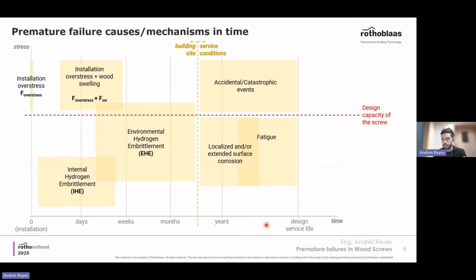We installed the fastener to the design service life. Many things can happen, and the environment and the context change. So the first thing that can happen is installation overstress. We can overtorque a fastener during installation, and that, of course, would mean that we are above the design capacity of the screws, and it breaks. It will break in dry conditions, because of an overstress. That happens, especially with an improper installation angle with an impact wrench, so an uncontrolled installation torque. In that case, we're above the design capacity of the screw. That happens instantly. Or we may add some tensions to the screw that would then mix with other factors that would lead to failure.